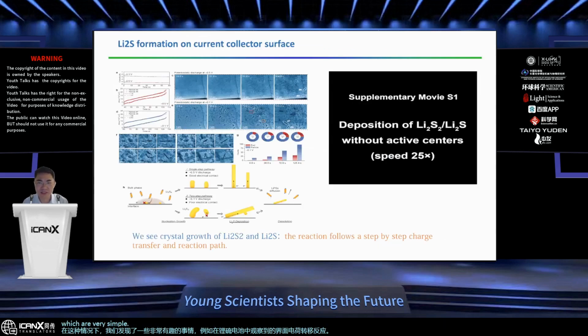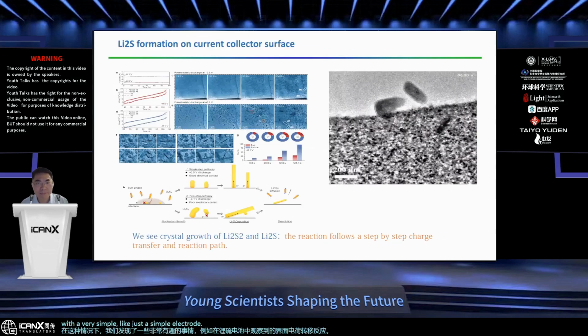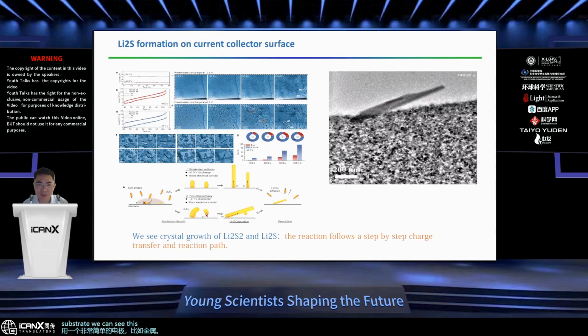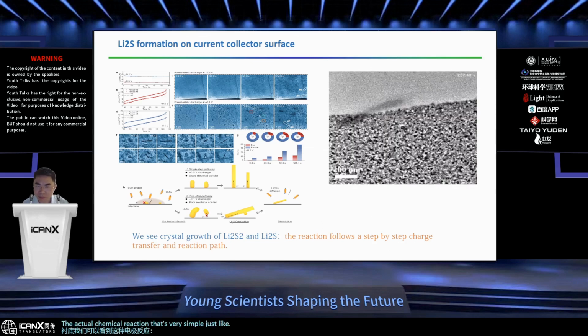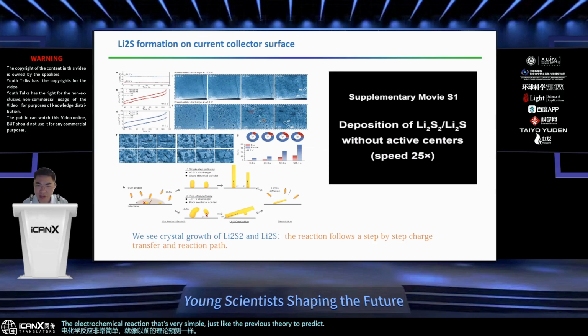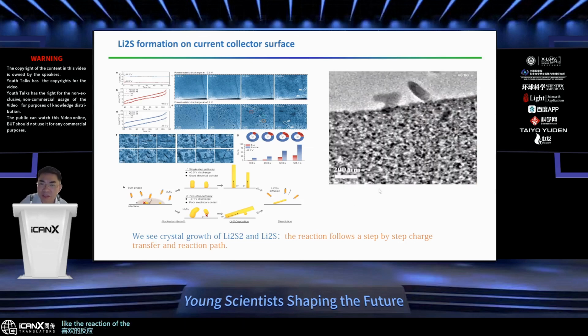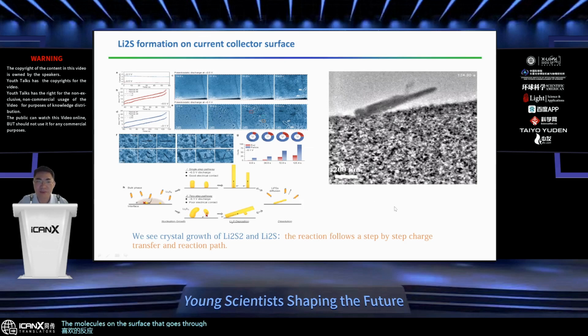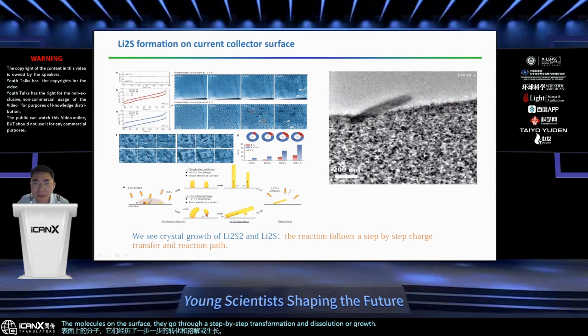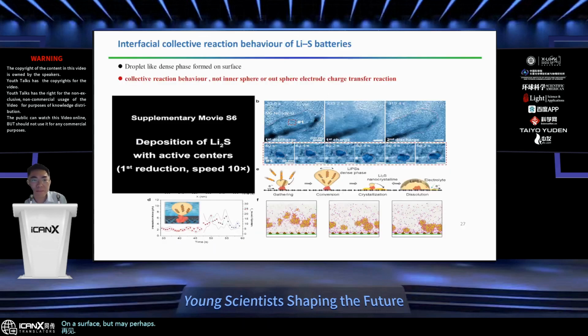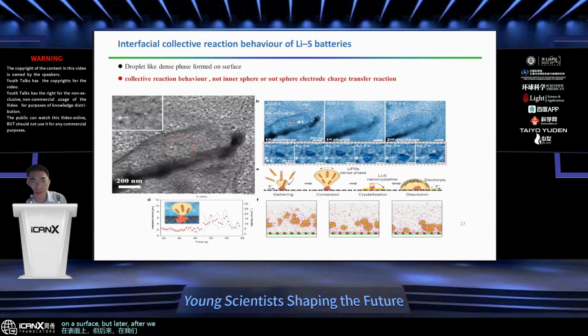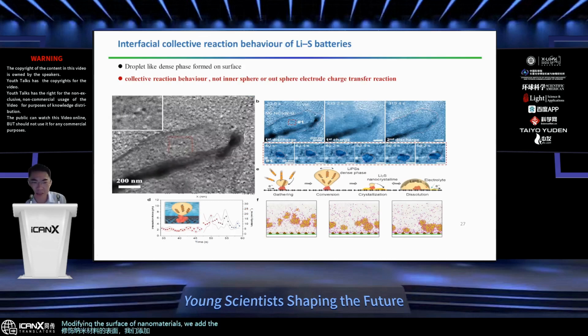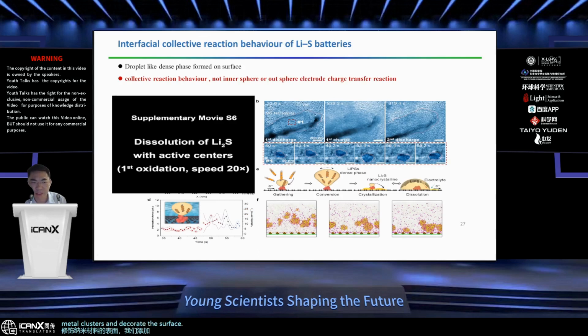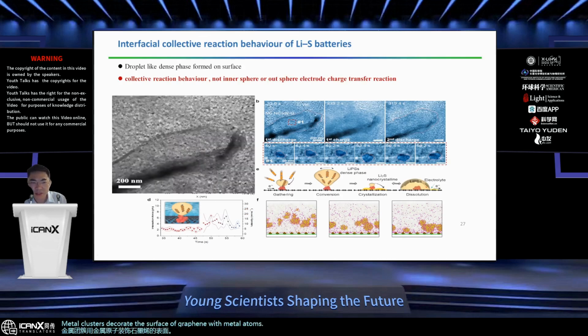With a very simple electrode, like a metal substrate, we can see this kind of electrochemical reaction. That's very simple, just as the previous theory predicts, like the reaction of the molecules on the surface. They go through a step-by-step transformation, and then dissolution or growth works on the surface. But later, after we modify the surface of nanomaterials, we add metal clusters and decorate the surface of the graphene with metal atoms.